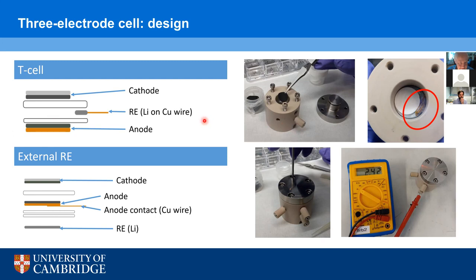So looking at the two different configurations that we're referring to, there's the T configuration where the reference electrode sticks out the side, like the base of a T, with a piece of lithium twisted into the copper wire, which has two separate cables. And this is the one that you can see in the top right of the photos, with a piece of lithium highlighted in red. So this is perpendicular to the direction of the main electrode stack.